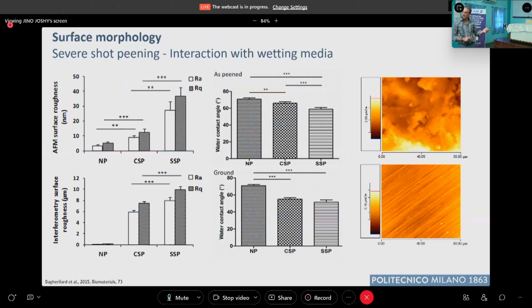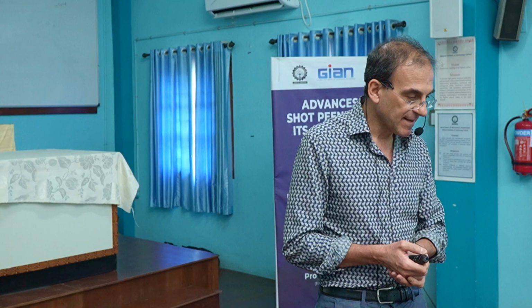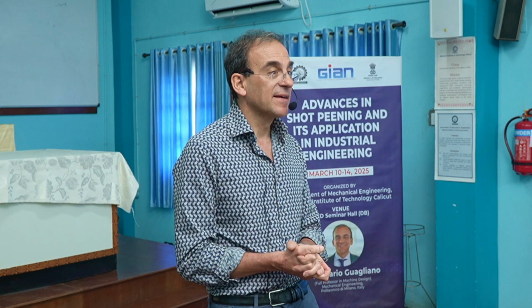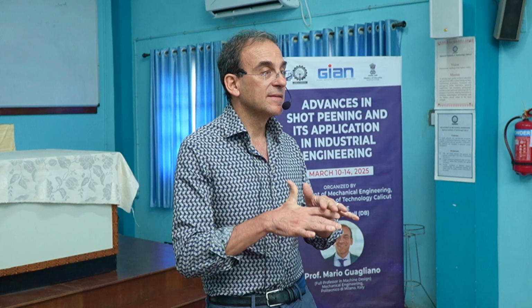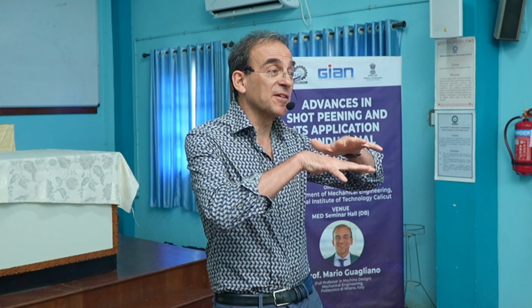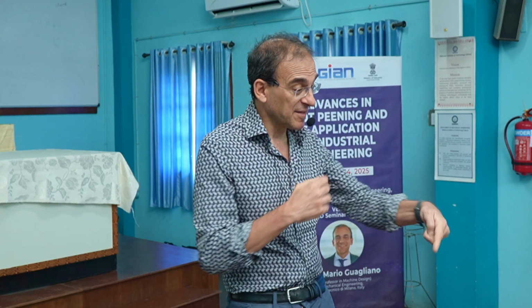Wettability, yes, sir. So here higher roughness actually gives lower contact angle. Am I right, sir? Here, the SSP has higher roughness, and in this case, yes, we obtain this result. And it gives lower contact angle, and lower contact angle means good adhesion. Yes, indeed, the drop is spreading more. And this is related to the result that I showed in the other slide, of course.